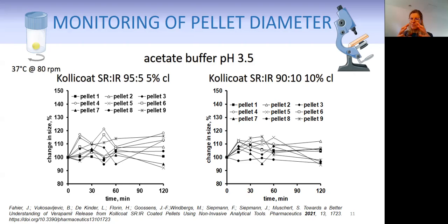So we investigated the increase in diameter of the pellets during dissolution of, once again, single pellets with a microscopic observation. And you can see that when we expose the coating blend, nevertheless the coating thickness, to acetate buffer 3.5, the pellets do not swell significantly. We've got some, like here, pellet number 9, which is swelling continuously. We've got others like pellet number 3, which is decreasing in size and then going up again. Actually, these ups and downs can also be attributable to the fact that the pellets have not been perfectly spherical. So here you can see that pellet number 5, however, is decreasing in size. So there actually, we could have a swelling, rupture of the film coating, which leads to a shrinkage of the pellet. But these phenomena were not quite significant.